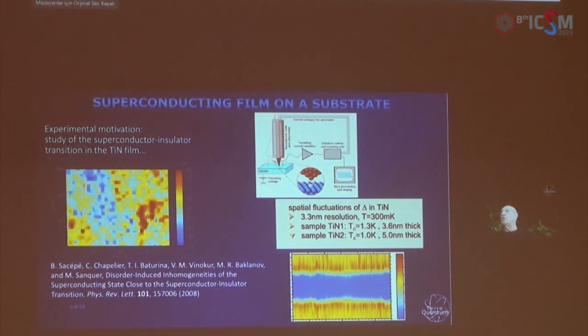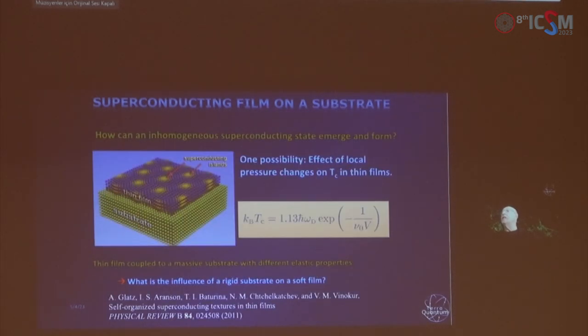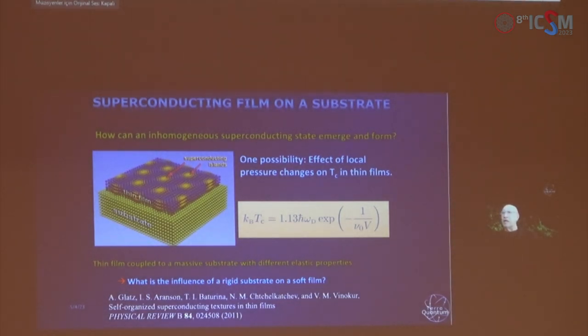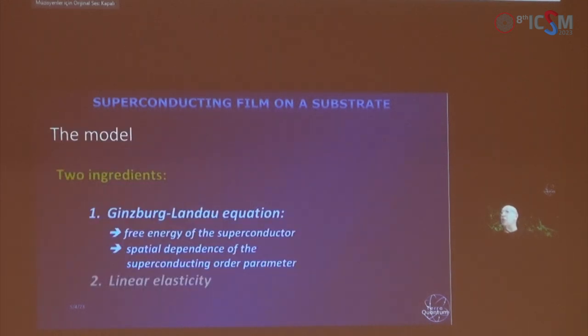Now, of course, it will be very interesting to check what we can get out of this understanding of superconductivity, and we had an experimental motivation for the next study: the discovery that superconducting films form a granular structure, superconducting grains connected to each other. So this was the experiment, and the model which we tried to consider was a little bit easier than the model of long-range Coulomb interaction. It was the model of a superconducting film which is connected elastically to the substrate, and therefore we have long-range elastic interactions between different points of the superconductor.